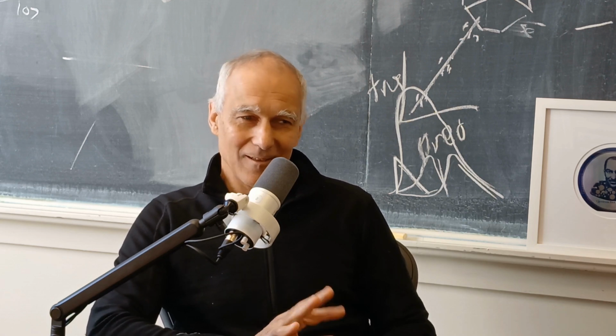So basically what Ekimov did, he got rid of everything that was extraneous. He just kept the silicon, the oxygen, and the elements that were going to form what he thought were the color-forming centers. And using small angle X-ray, where he was able to measure the size of particles in the sample, he was able to correlate the particle size of particular compounds with color, with spectrum.